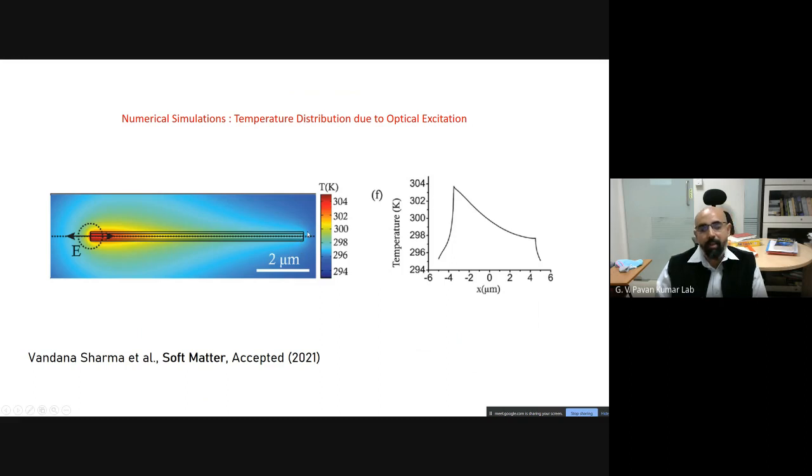The silica colloids happen to be thermophoretically interacting with this structure, and therefore they move from a lower temperature to the higher temperature, indicating that there is some kind of thermophoretic interaction. Because if you use a similar situation and replace a silica colloid by a polystyrene colloid, which has the opposite sign of the Soret coefficient to the silica colloid, they do not exhibit such a pulling motion, and therefore this indicates that there is an optothermal effect associated with this situation.